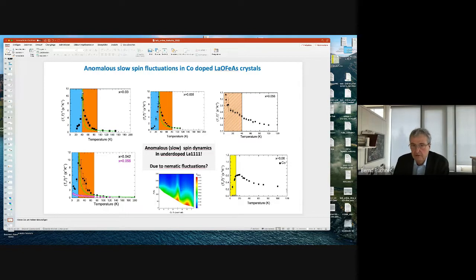So slowing down of spin fluctuations, long range order, and then you end up hitting this blue region. And this you can follow as a function of doping, no problem. That's what you expect for long range order. If you then go slightly above this critical point, so here for this doping, this strong peak disappears, but we still have a very, very strange temperature dependence. You still see this increase here of the relaxation rate.